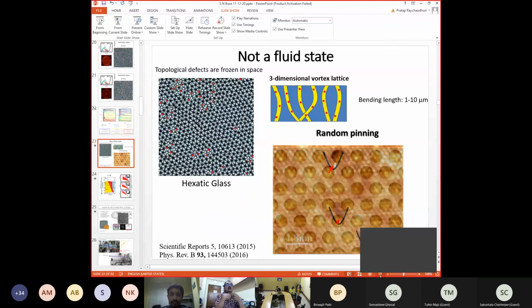And the pinning prevented the disordered state from becoming a fluid. It remained in a glassy state. So if you want a very rough analogy, the pinning played the same role as glass formers play in actual glasses. For example, when you have borosilicate glass, you have to put in that boron, which acts as the glass former. That actually prevents long range order from establishing. Here the pinning is doing the same thing.